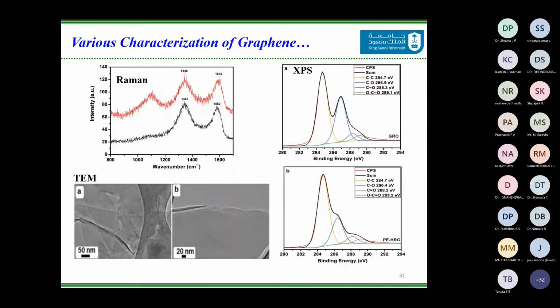when you make the graphene oxide, you destroy the sp2 structure of the graphene. However, when you reduce it, there is restoration of the sp2 structure, which is evident because these two are very much similar, and the difference between these two values is 10 per centimeter. So it means that the highly reduced graphene that you obtain chemically, and the plant extract obtained graphene are almost similar.